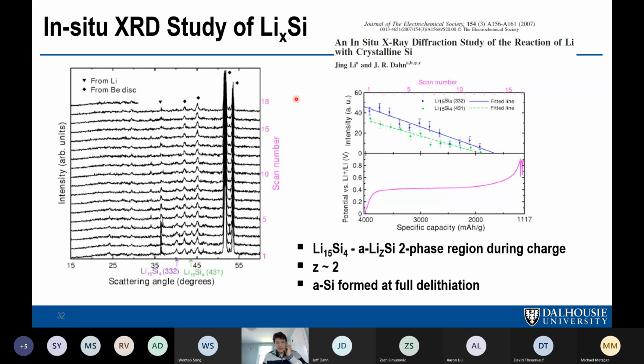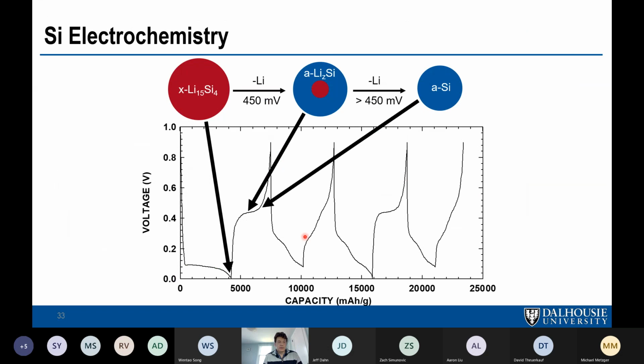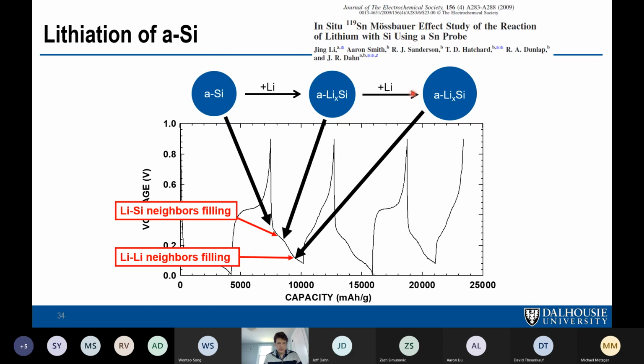So during delithiation, the 15-4 phase delithiates in a two-phase region with amorphous lithiated silicon, just as you would guess from the voltage curve. That was verified again by in situ X-ray diffraction. So during delithiation, you form another two-phase region. Again, you get these huge stresses inside the particle, and eventually you form amorphous silicon. Then amorphous silicon does not lithiate like crystalline silicon did. It lithiates in a single phase region.